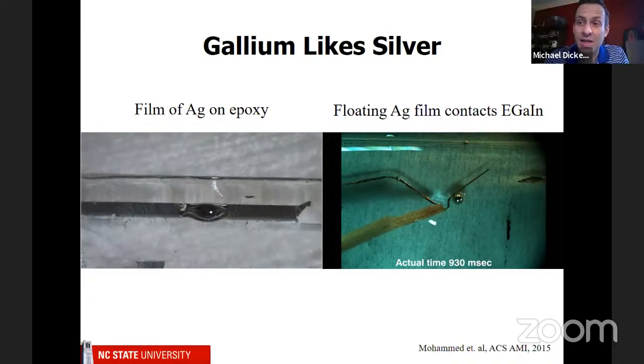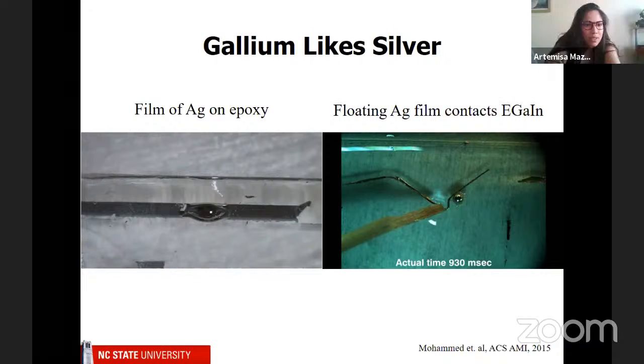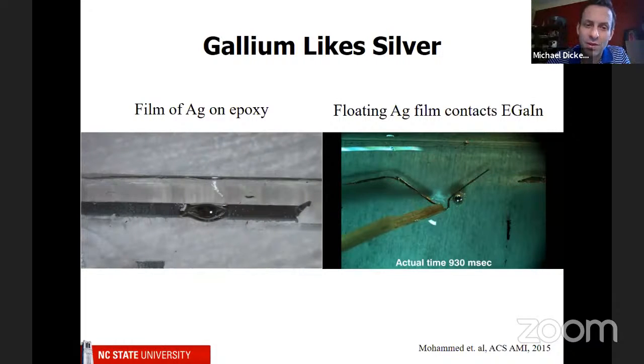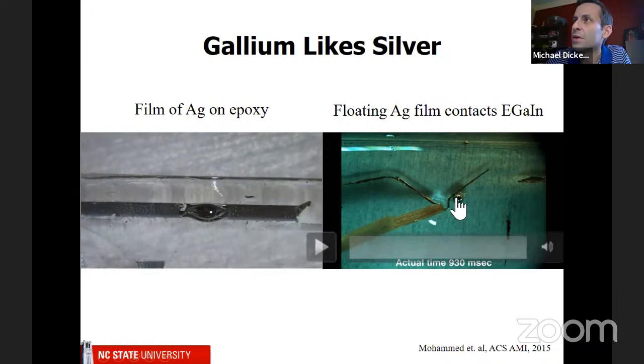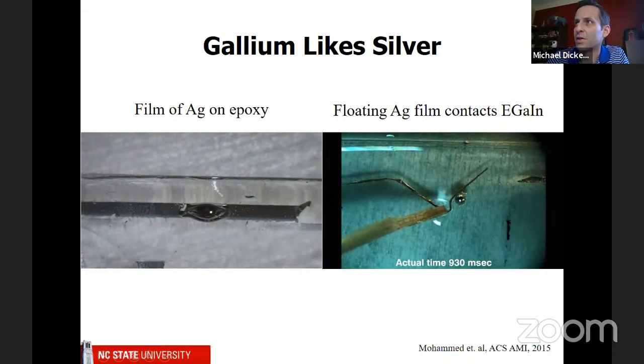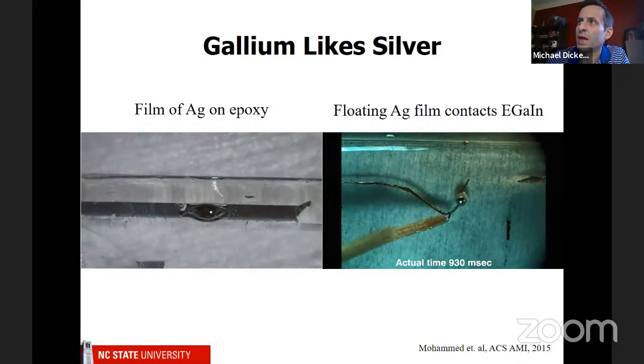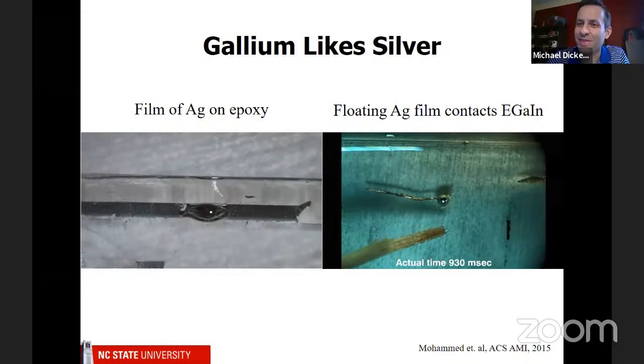Now, if you take that same piece of silver and have it floating in solution like a noodle, that's what you're seeing here. If you take a little piece of wood and touch the liquid metal, here's the liquid metal, here's the little piece of silver, and if you touch it, the gallium wets the silver and it actually pulls it into the gallium. It sort of eats it.